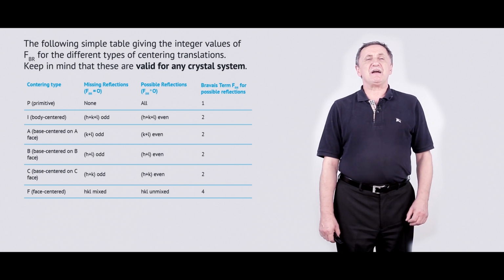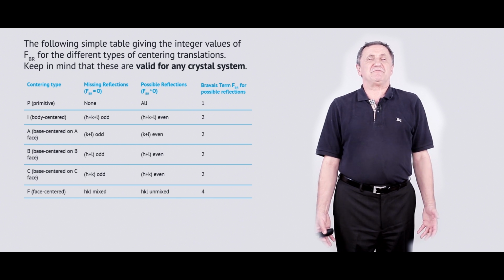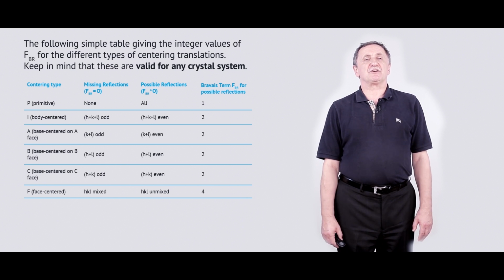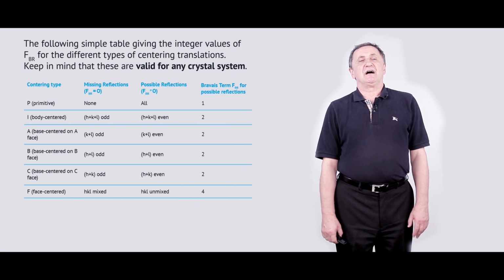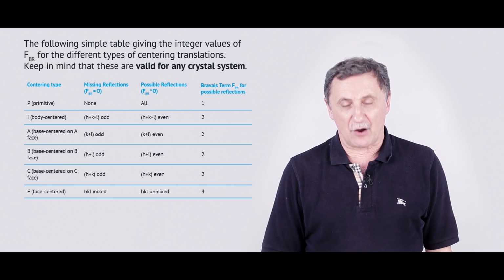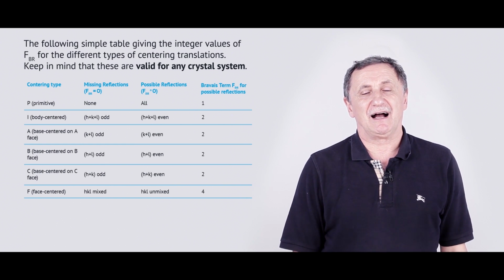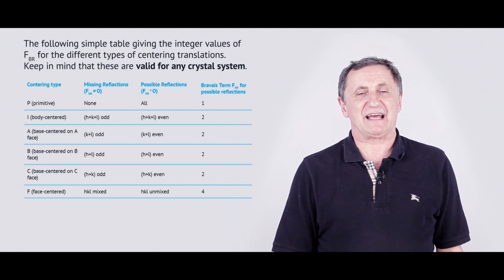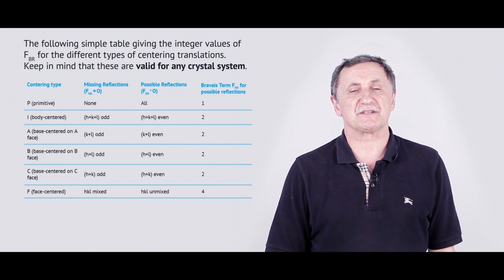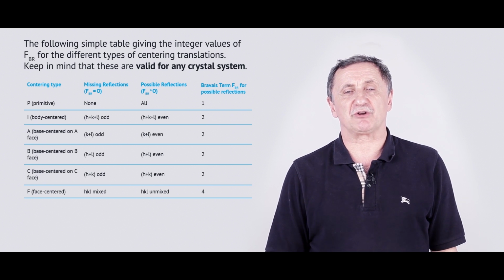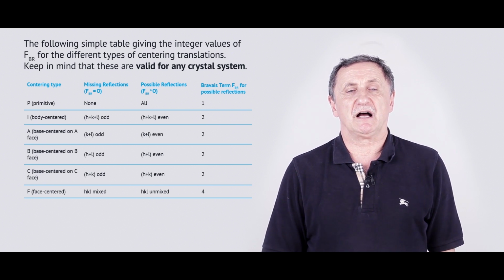However, in more difficult and more common cases, when we have the body centered, or the base centered, or the FCC face centered structures, there is a restriction on the peaks, which is related to the interaction of the beams diffracted from different atoms inside this relatively complex cubic structure, if you want. And this table demonstrates what kind of restrictions you may have.